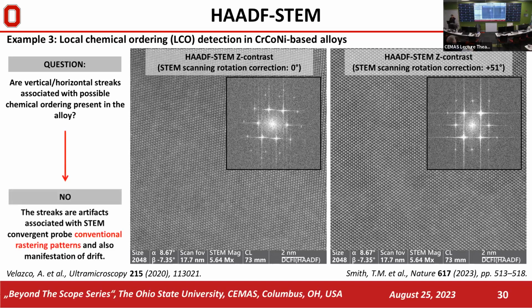it's just an artifact which is associated with conventional rastering pattern, which is set as standard for the systems as they're produced, and this can also be associated with drifts in specific situations. So if you're more interested in this artifact, please find the paper in Ultramicroscopy in 2020. So we are pretty sure that we are not seeing any ordering in the case of CrCoNi alloy.